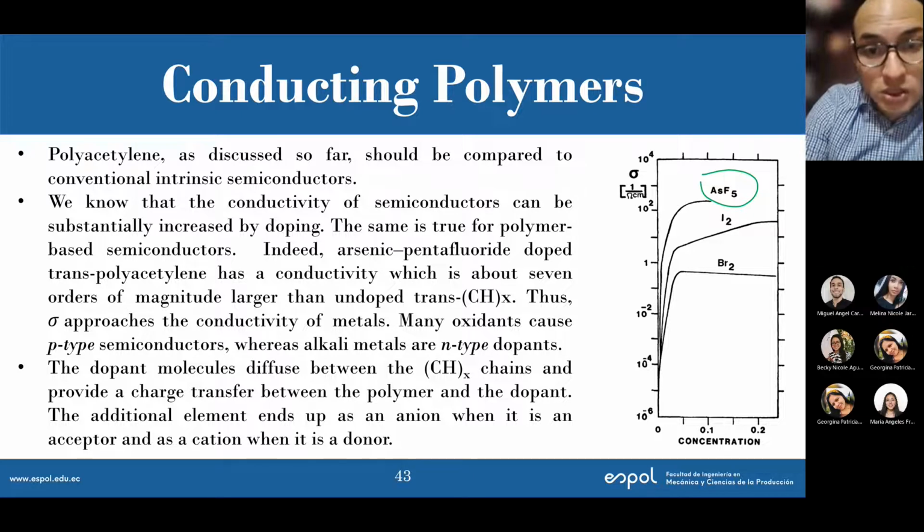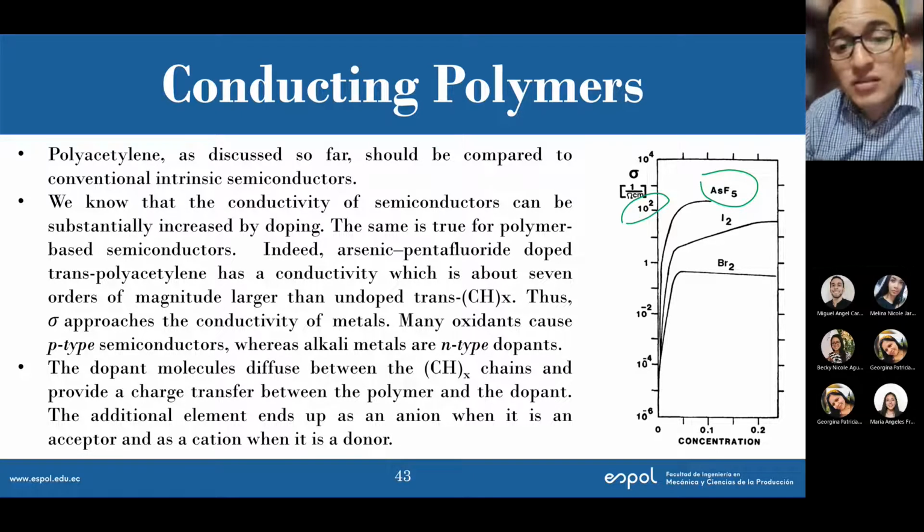And look at that, you get a conductivity of close to 500 1/Ohm per centimeter. Just quite a nice value of conductivity. That would be the conduction of a poor metallic conductor. So it's basically around what a conductivity of a doped semiconductor will have. Maybe a bit lower, but around that.